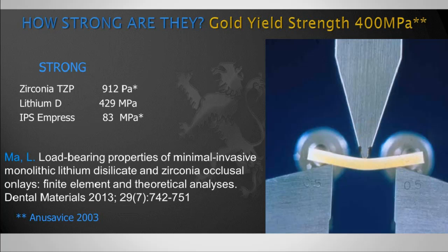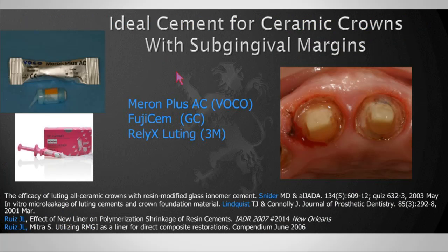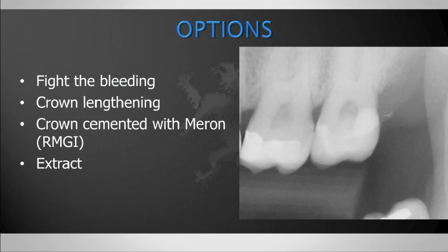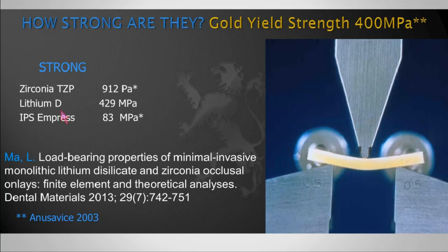But then let me go back here. Then what crown do we want to use? Now, based on this slide, if you use lithium disilicate and you cement it with a resin modified glass ionomer, then we are losing half of the strength, because the literature shows that lithium disilicate, when it's cemented and not bonded, has about half of its strength. So that might be a little bit dangerous, especially in the molar area. I can tell you that I cemented a number of lithium disilicate or Emax crowns, and I've had a few that broke when I cemented them.